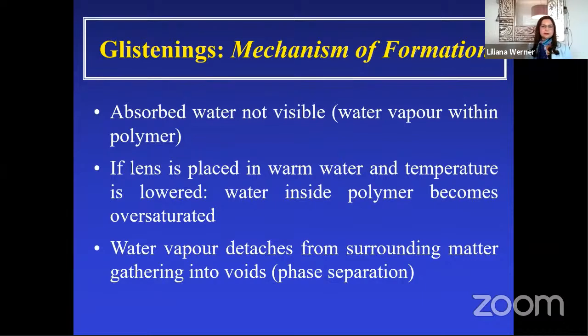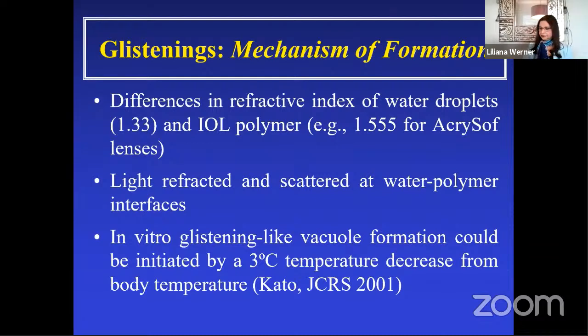If an IOL is immersed in warm water and then the temperature is lowered, the water vapor inside of the polymer becomes oversaturated and detaches from the surrounding matter, gathering into the voids. As there are differences in the refractive index of the water droplets and the IOL polymer, the light will be refracted and scattered at water-polymer interfaces, which is seen as glistenings. Studies have demonstrated that a decrease of 3 degrees Celsius from body temperature can initiate the formation of glistenings.